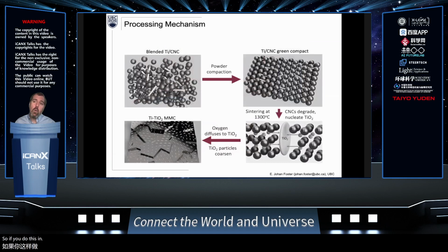Okay, so if you do this in the wrong way, it will act as a source of oxygen, I suppose. But what we found was that the CNCs degrade, if you do this in a controlled manner, and nucleate the growth of titanium oxide within the titanium. So if you do this in a controlled way, the oxygen diffuses to these points. So it's no longer a cellulose nanocrystal. We've degraded it, but it acts as a nucleation point for the growth of titanium oxide within that titanium. They coarsen, so they get bigger and bigger as you do this more and more. That pulls oxygen out of the interstitial sites of our titanium.